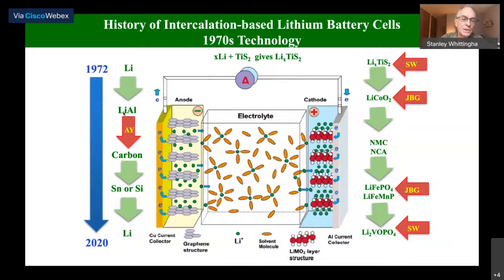Exxon eventually switched to lithium aluminum because of the possibility of dendrites and fires. And then Akira Yoshino was working at a carbon company, switched to a carbon-based anode. And this again is what I show you here. This is graphite structure. So you can store the lithium within the graphite.